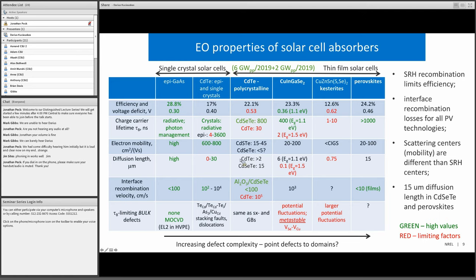Diffusion length is the product of mobility and carrier lifetime. And in both cadmium selenide telluride as well as in perovskites, these diffusion lengths could exceed 10 microns, could be in the 15 micron range. Because the absorbers are only 2 to 3 microns thick, these diffusion lengths are sufficient for very high efficiency solar cells. Also, these high diffusion lengths mean that both sides of the solar cell need to be passivated very well. The back contact passivation is becoming increasingly important when the carrier diffusion length becomes very high.